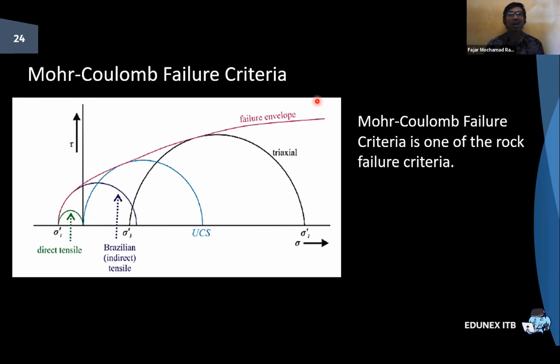process. Now, in the drilling process, if the mud weight used is lower than the shear failure or collapse stress, the shear and compressive damage that occurs in the wellbore in the direction of the minimum horizontal stress can cause a breakout. And if the mud weight used exceeds the tensile strength of the rock, there will be a tensile crack induced toward the maximum horizontal stress, or fracking.